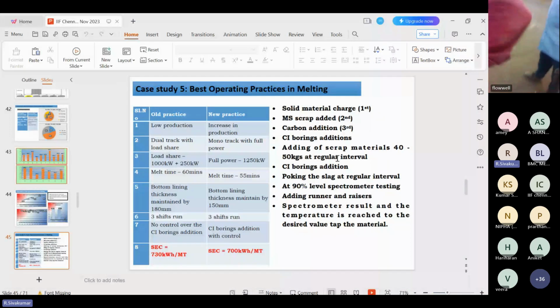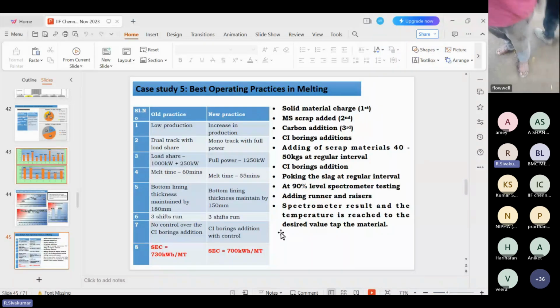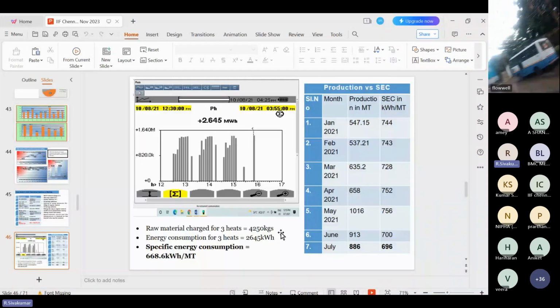So in such a way the operator pokes the furnace at regular intervals and removes the slag. At the 90% level, the spectrometer testing is to be done, and the runners and risers are added. Then based on the spectrometer result, and when the temperature reaches the desired value, the material is tapped. So due to these practices,